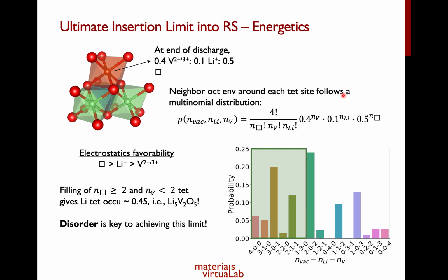And if you actually plot it out, this is the graphical representation of these multinomial distributions for different combinations of number of vacancies, number of lithium, and number of vanadium, right? Now, just from a very simple electrostatics argument, we can argue that it is more favorable for that tetrahedral site to be occupied if you have vacancies beside it, as opposed to having lithium plus, and of course, if you have vanadium, it is going to be the least favorable, because vanadium is in either a 2+ or 3+ oxidation state, okay.